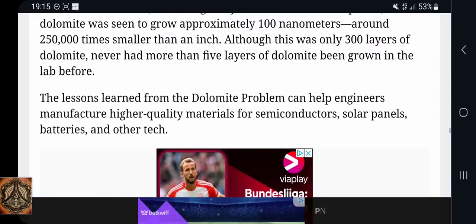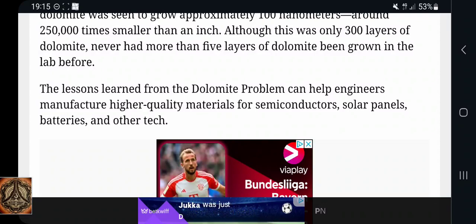After placing a tiny dolomite crystal in a solution of calcium and magnesium, Kimura and Yamazaki gently pulsed the electron beam 4,000 times over 2 hours, dissolving away the defects. After the pulses, dolomite was seen to grow approximately 100 nanometers, around 250,000 times smaller than an inch. Although this was only 300 layers of dolomite, never had more than 5 layers of dolomite been grown in the lab before. The lessons learned from the dolomite problem can help engineers manufacture higher quality materials for semiconductors, solar panels, batteries, and other tech.